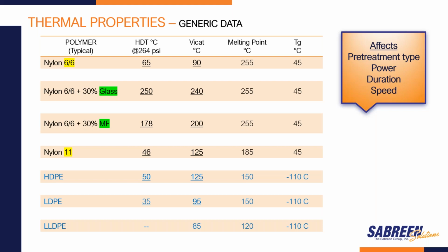Well, let's say we already have our pretreatment, and now we bring on another product, and this is going to be nylon 6/6. This is the top row. Well, now our heat deflection temperature is 65 degrees centigrade with a Vicat softening point of 90. So if we have our identical pretreatment process set up, then we have much lower softening points and much lower deflection points, and so that pretreatment is still putting out as much heat, and that's why it's so important that you have to know not only the polymer that you're using, but also what the thermal properties are.